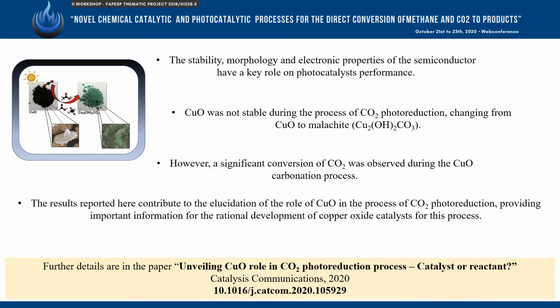Copper oxide was not stable during the process of CO2 photoreduction. It changed from copper oxide to malachite. However, a significant conversion of CO2 was observed during the copper oxide carbonation process.